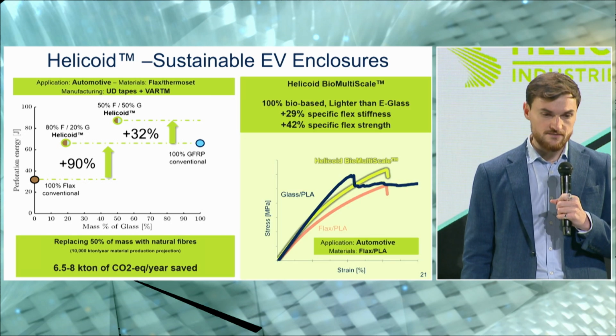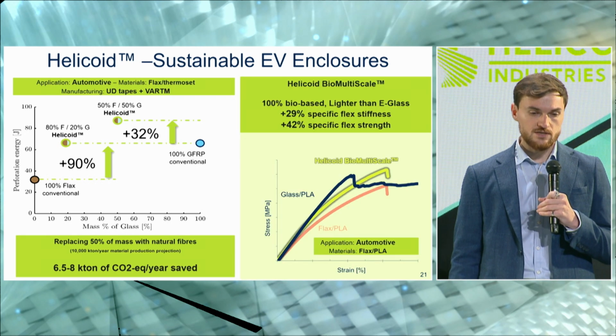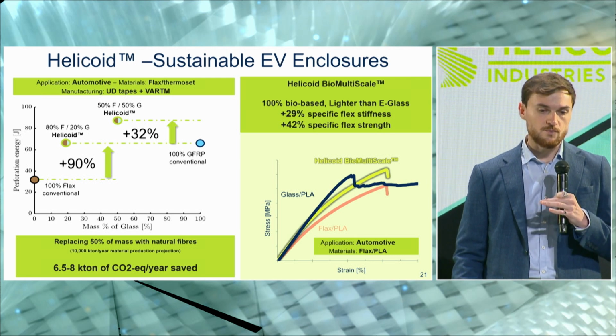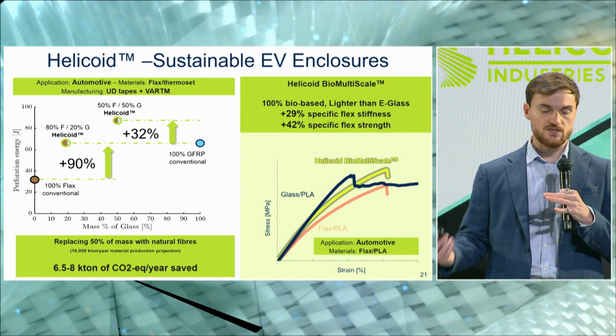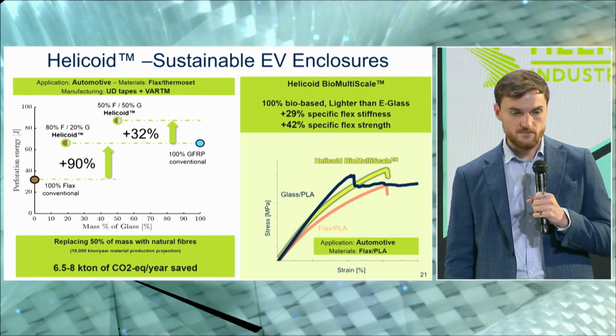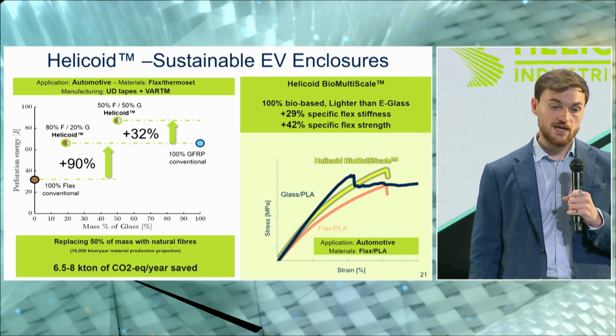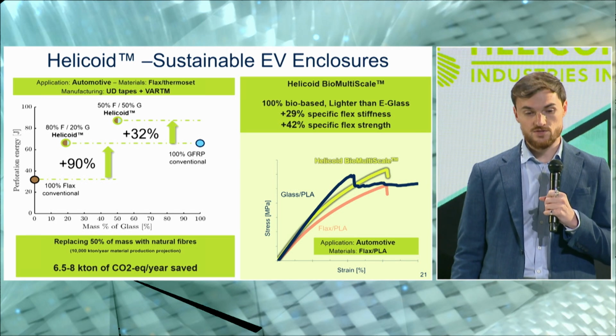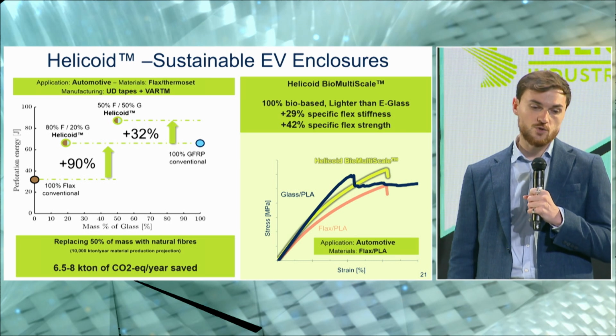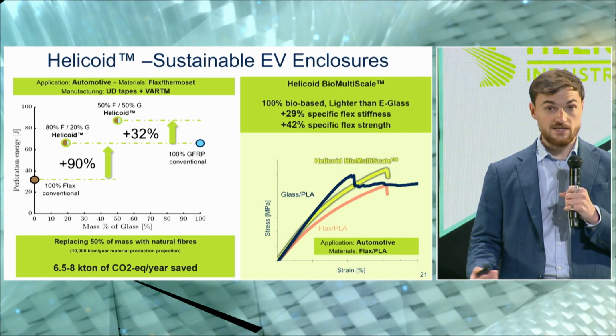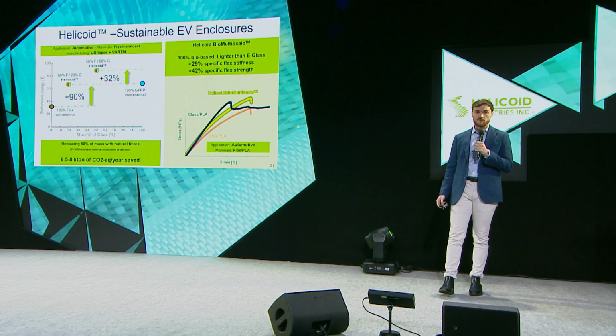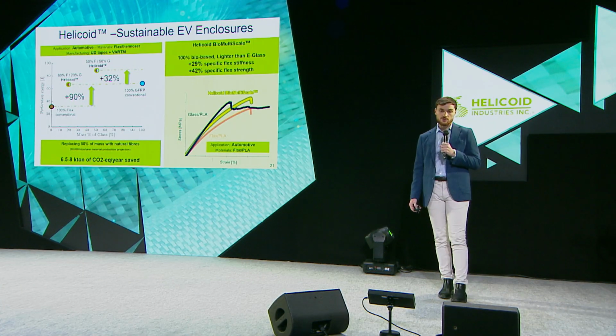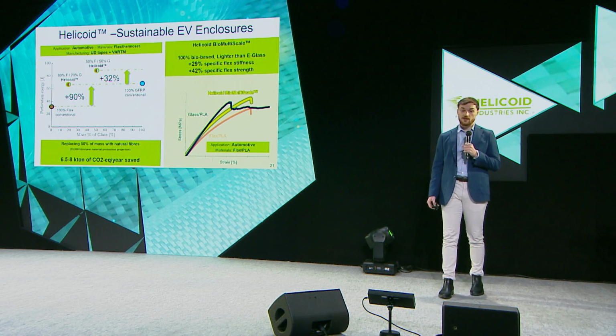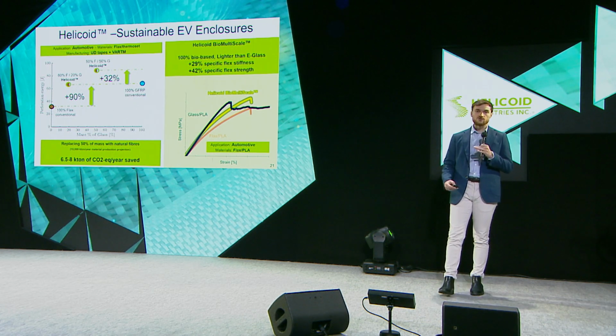We are also developing something which is more related to building up hierarchical composite, where we use 100% bio-based additives to the natural fibers that allows us to overcome performance of glass fiber solution. This is a stress versus strain obtained from a flexural test using a PLA as a resin, where we are able to overperform a glass fiber PLA solution, while our solution is 100% bio-based. So again, this is how, through our technology, we enable more sustainable materials in high-performance applications.